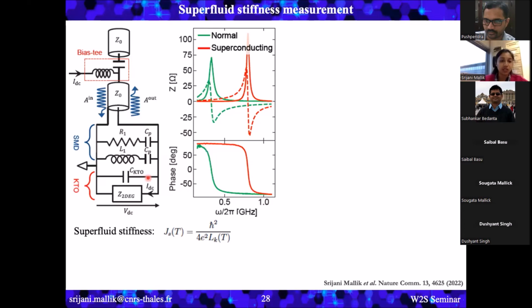Now at the normal state, we just have contribution from this inductance. But at the superconducting state, we have one extra contribution in the inductance. That's the kinetic inductance of the 2DEG.